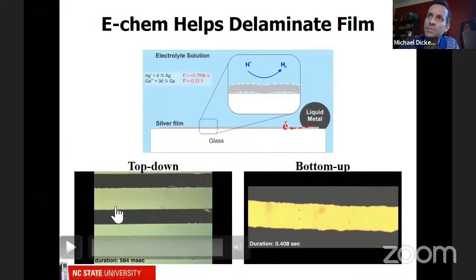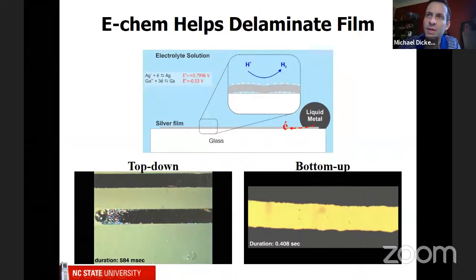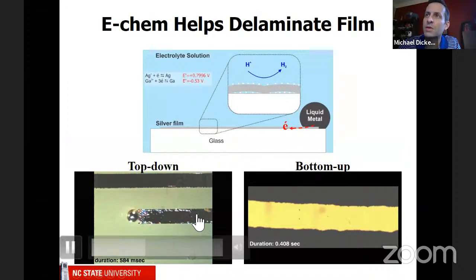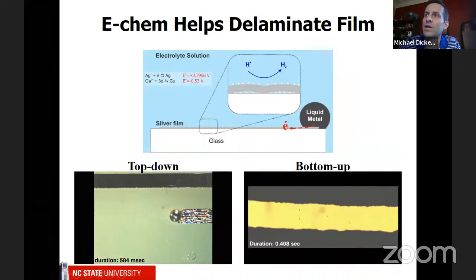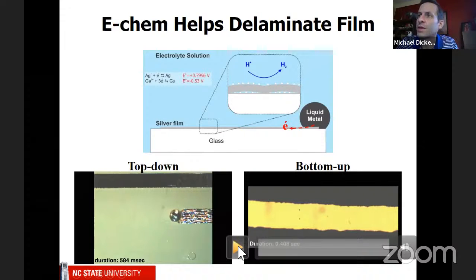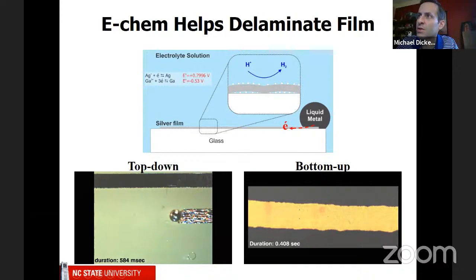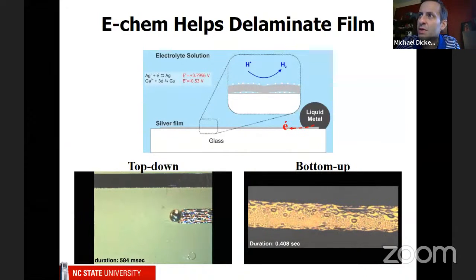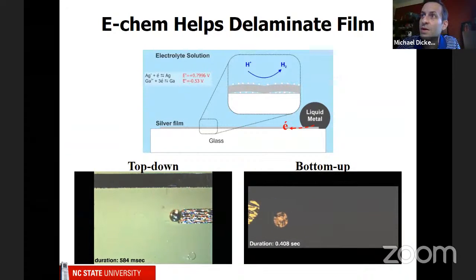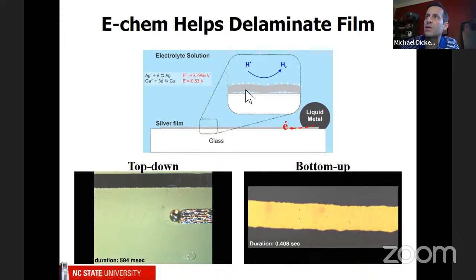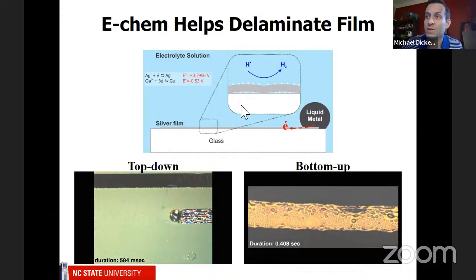And so if you look top down, this is again a high-speed camera, you'll notice as the liquid metal comes along, that film sort of wrinkles before the metal gets there. And so I'll just let it play one more time. So you can see even over here, the film is wrinkling. So then we looked from the bottom, and again, as the liquid metal comes along, you can start to see bubbles form. And amazingly, these bubbles are forming between the metal film and the substrate. So that means these electrochemical reactions are occurring between the metal and the substrate, that's shown here. And I think that helps to lift the film off of the surface.